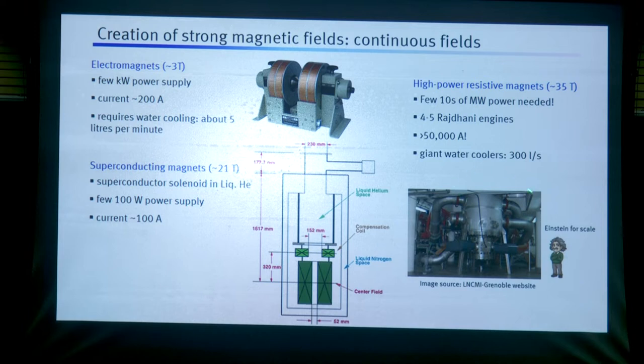So then we go to some special facilities, such as one is in Grenoble. So this is a huge magnet compared to the height of Einstein here. This would be like 3 times higher. A huge magnet, and then there are these tubes which are used for running water through them. You have to run 300 liters of water per second to cool this down, because this becomes very hot. You use actually tens of megawatts of power with which you can run a small city.